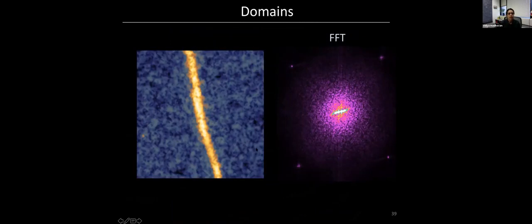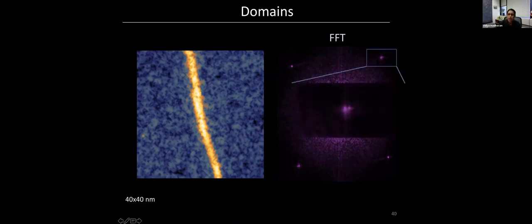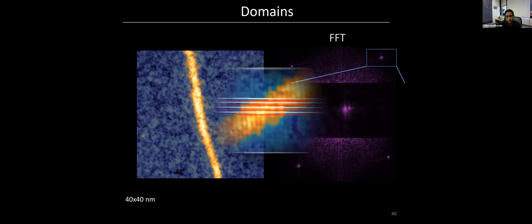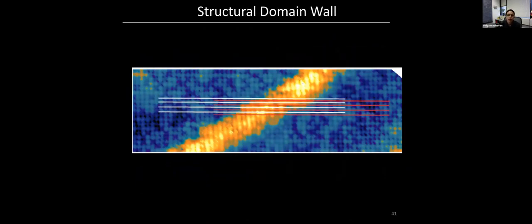So one thing is you take a region, a topography like this, and you do a Fourier transform. You immediately see that, if you zoom in here, this is the atomic lattice. And the fact is that you have these two dots. The presence of a split peak in the Fourier transform indicates that these two sides are actually two different domains. It doesn't tell you there's a pi phase shift.